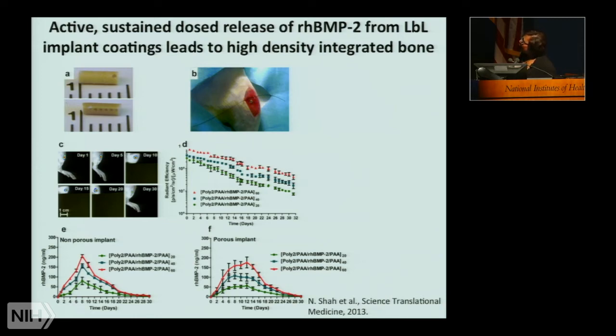So here you can see the plastic implant that we used, which was PEEK, and PEEK with holes drilled in it. What we did was we coated these two examples, which represent a smooth implant and what we were trying to replicate as a textured implant, with BMP2 that was labeled with a fluorescent protein. So here we can actually see this release over time, and it's a little bit dark here, but you can see that it's releasing over a period of 30 days. If we look at the radiant efficiency over time, we can see that the release is actually quite constant, and it's taking place over this period of a month fairly consistently.